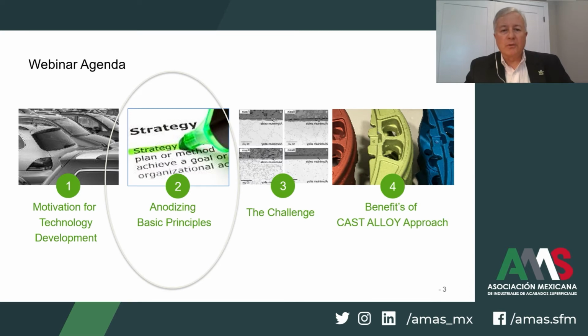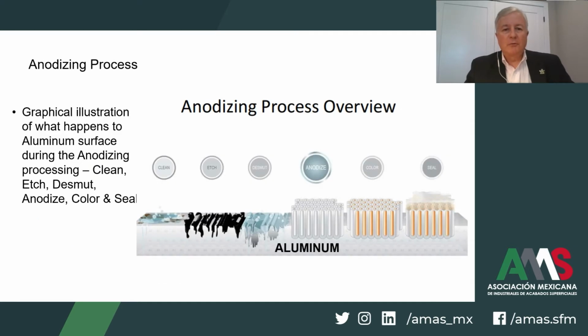In the next part of the webinar, to understand how anodizing cast alloys works, we'll do a quick review of some anodizing basic principles so that we can understand how these processes will work. For the creation of anodic oxides, here is a nice graphical illustration of what happens to an aluminum surface during an anodizing process in a traditional sense. So it's always important to clean the surface, then etching of the surface is done to remove surface defects. During the etching, the alloy element smuts form. This is the difficulty with cast alloys and the reason why desmutting the surface is very critical for allowing the anodizing process to build the proper oxide and the pore structure.